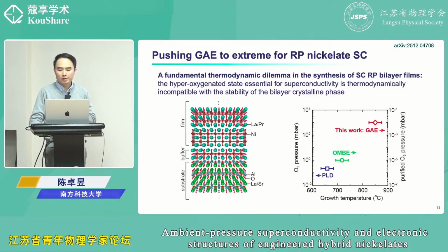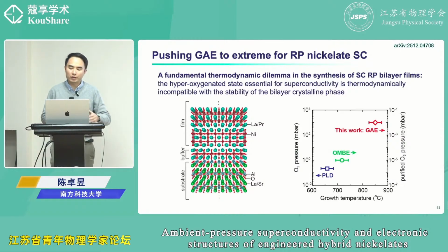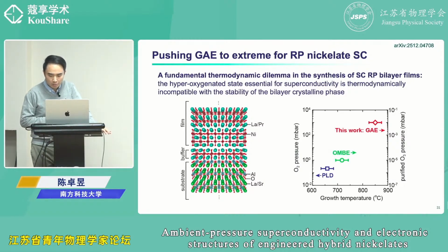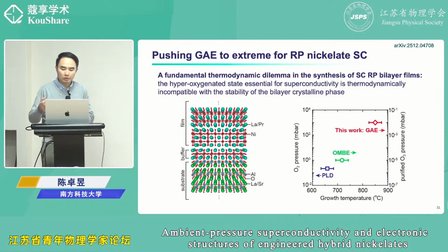That means the thermodynamic condition for a good crystalline phase is not the same as the requirement for the oxidation state required for superconductivity. So to decouple this conflict, what people usually do is use a two-step strategy for PLD or for OMBE methods.